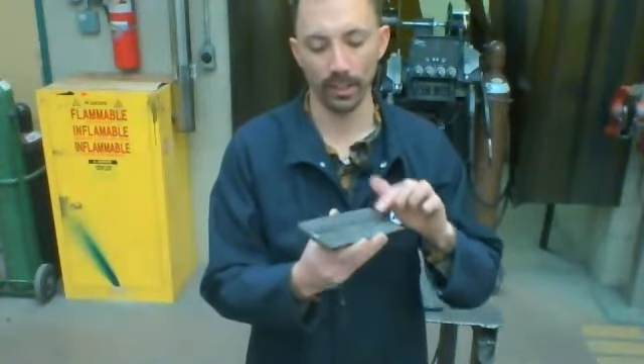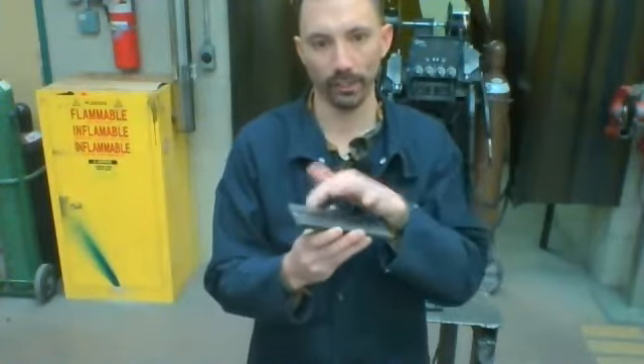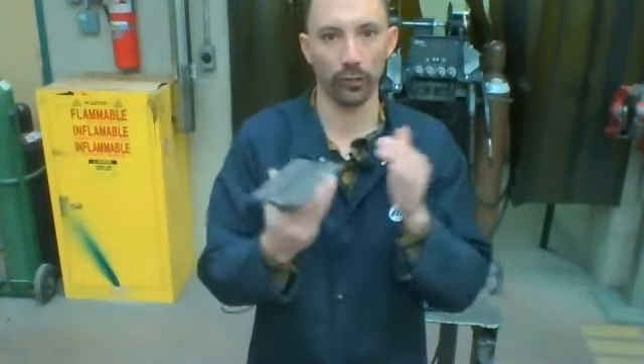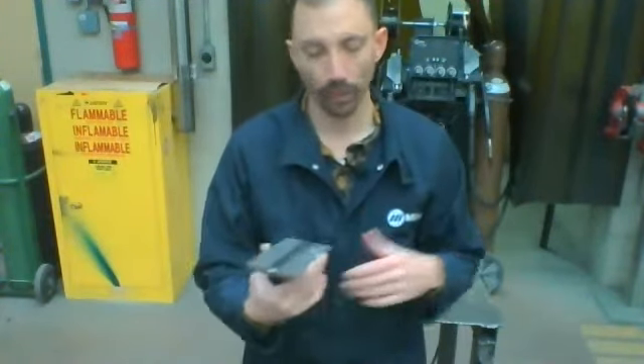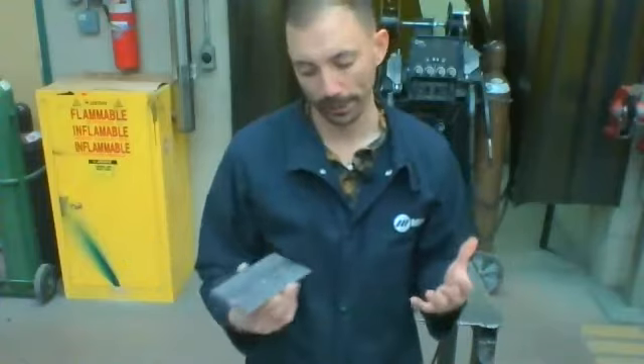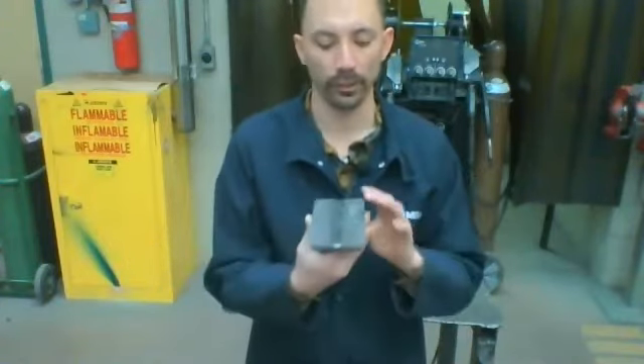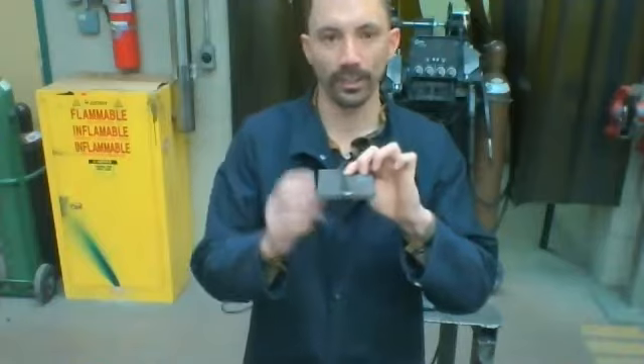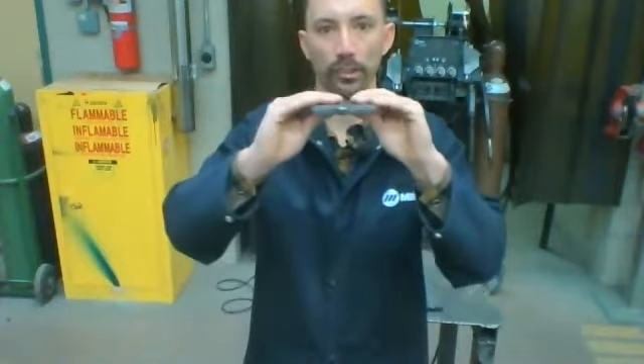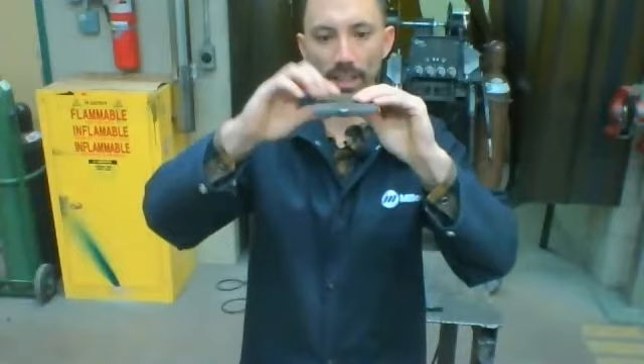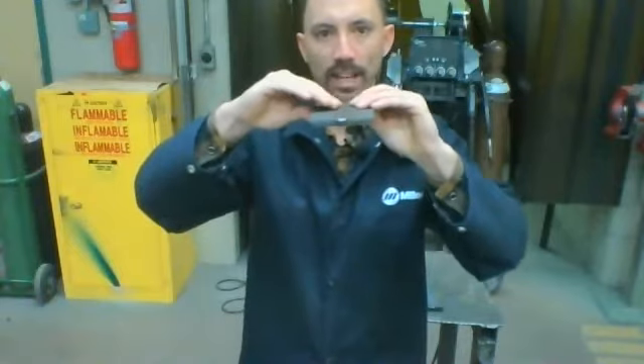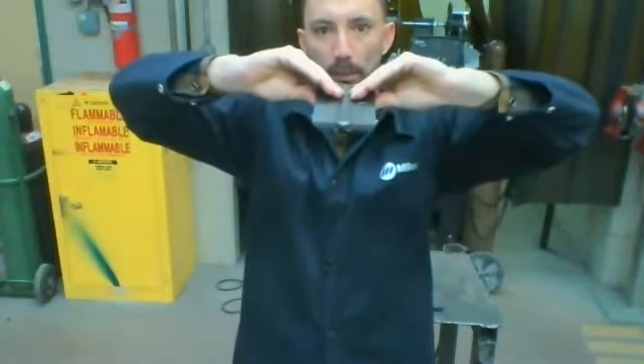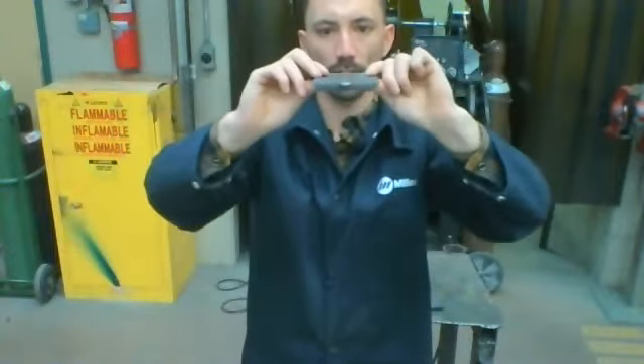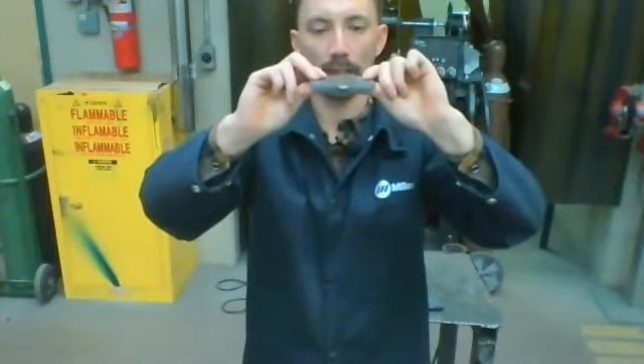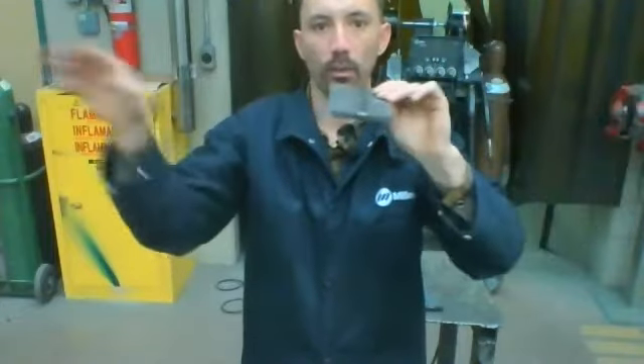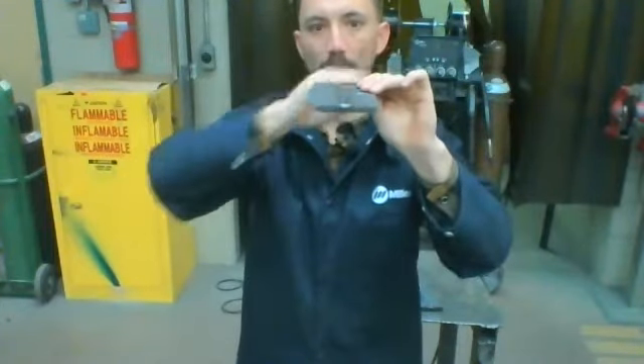We've seen that kind of, where that slag will crack on the sides. We can kind of flick it off. That's because the steel has shrunk somewhat. Because obviously hot things expand, cool things contract. And what happens here, though, is as this contracts, it actually imparts stress on this plate, and as this weld shrinks here, it pulls the edges of the plate up just a little bit. Now, it's hard to see on such a small distance, but if we were to have these longer, we would actually be able to see the slight bit of stress in there.